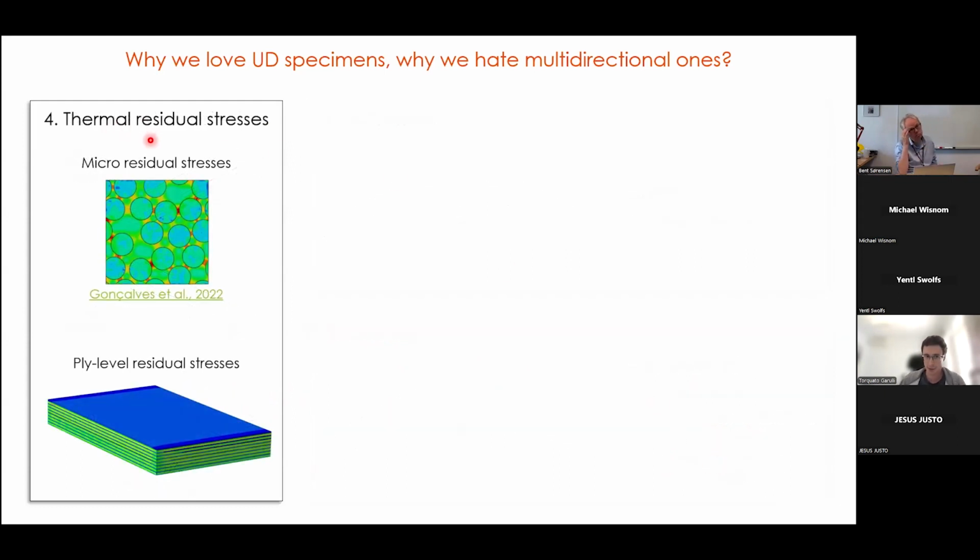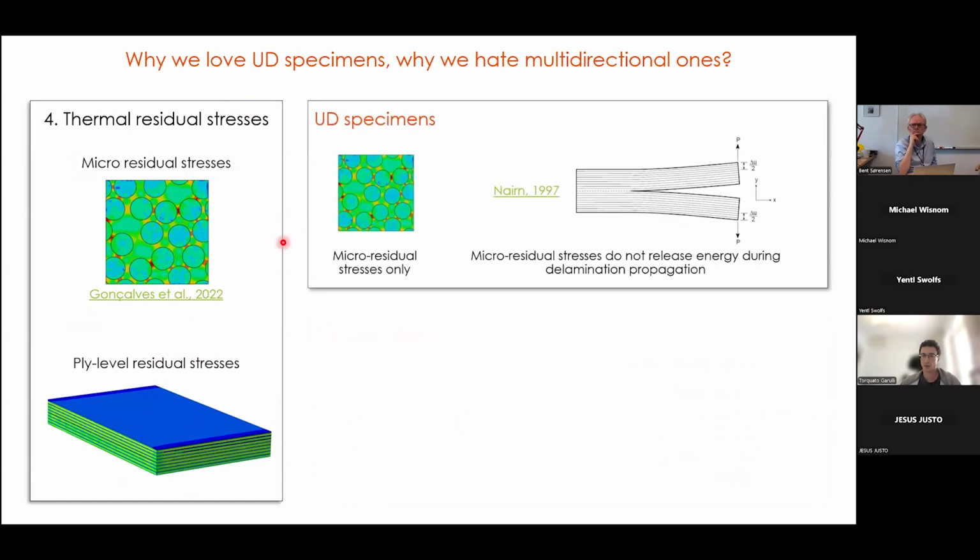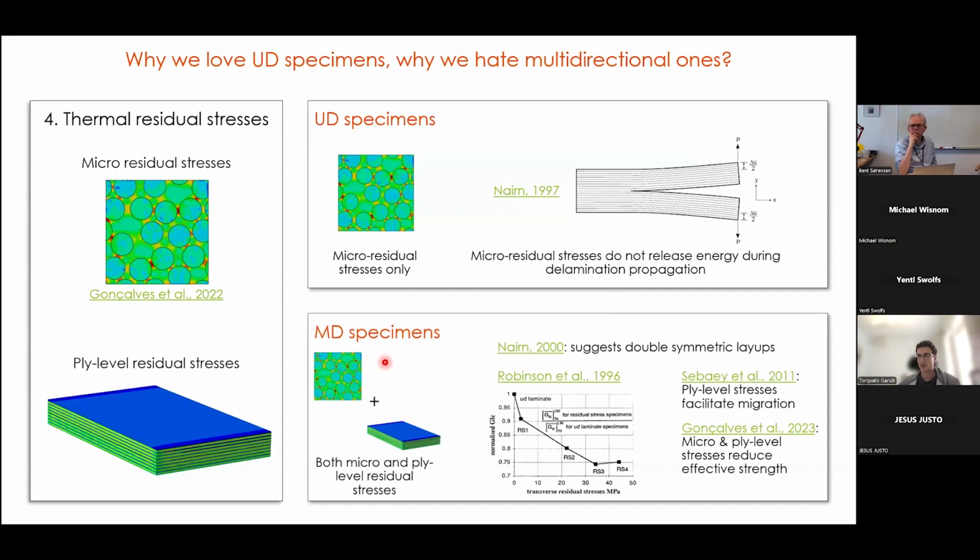Finally, another reason could be the presence of thermal residual stress. We know that this will develop both at the microscale and at the mesoscale in the case of multi-directional laminates. So for the unidirectional specimen, we would only have micro residual stresses, and it's been proven that this should not affect the fracture toughness. On the other hand, for multi-directional specimens, we will have both microscale and mesoscale stresses, and